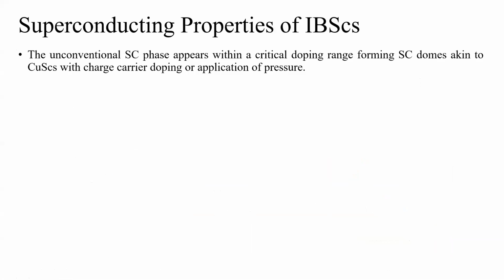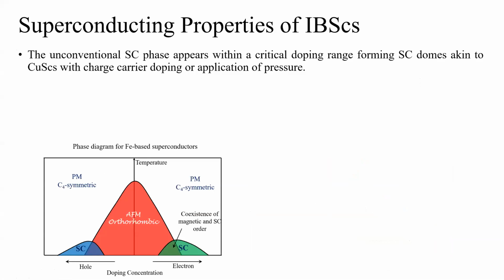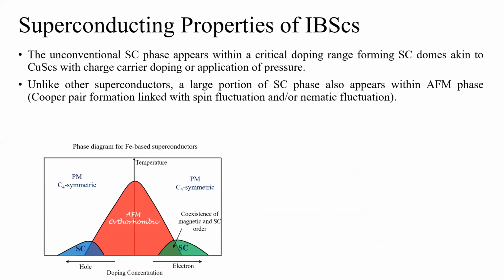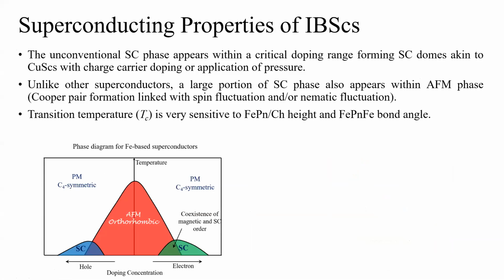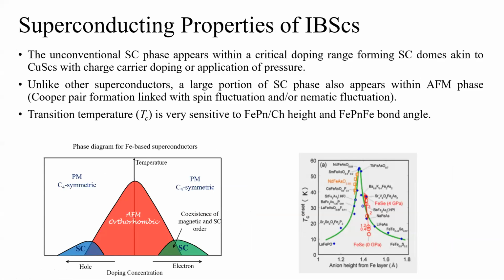So what are the superconducting properties? Of course, these are unconventional superconductors, and they have a superconducting dome very similar to copper-based superconductors. And unlike other superconductors, there is a part of the phase diagram where superconductivity and magnetism both coexist. The Tc that we observe is very sensitive to the iron pnictide or chalcogenide height or the iron-pnictide-iron bond angle. The compound shows maximum Tc at a pnictide height of around 1.4 angstrom, and the bond angle is around 103 degrees. If you change these bond angle values a little bit by applying pressure or replacing an atom in this compound, the bond angle or bond height will change, and the Tc will also change.